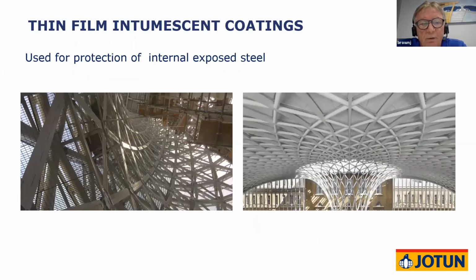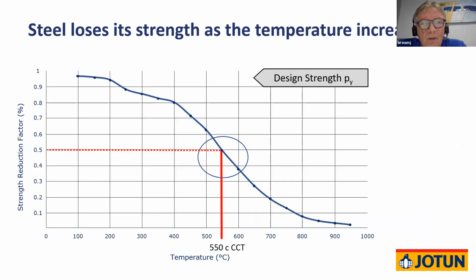And these products are used extensively where you've got steel exposed as an architectural feature. Airports, shopping malls, train stations, they tend to leave the steel exposed. And this is where we'd use these products. If we look at steel, its strength factor starts to reduce at a temperature of around about 550 degrees C. This is called the critical core temperature. So steel at 550 degrees C has lost nearly 50% of its structural strength.